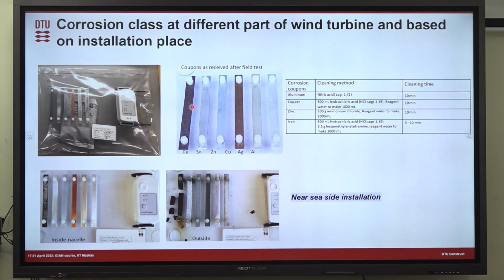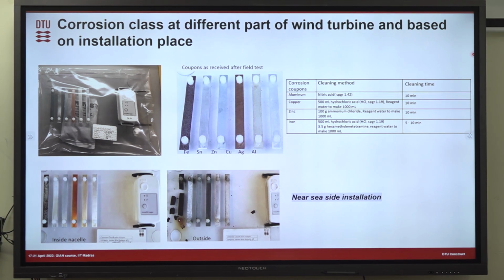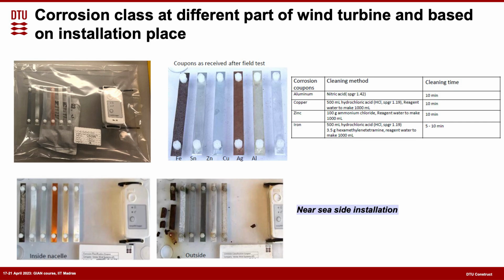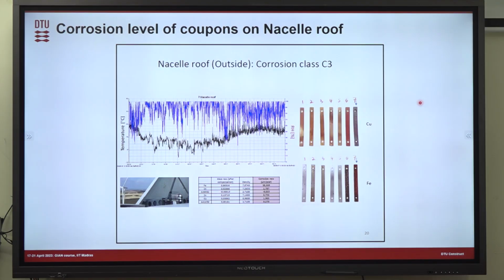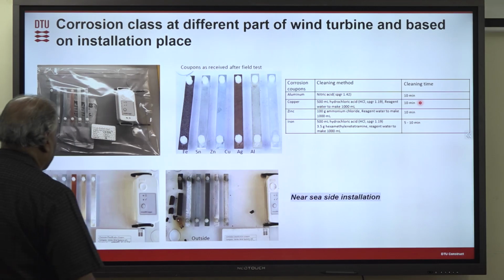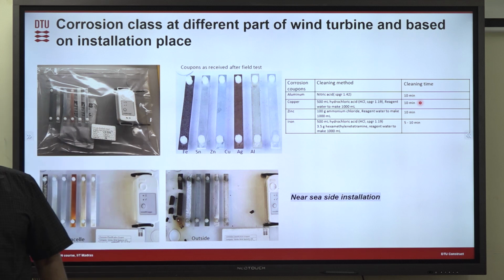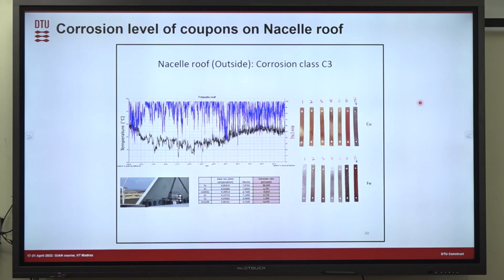So what we do is take these coupons and remove the corrosion product by a cleaning method. For copper and silver, we can also do an electrochemical reduction process, to reduce the copper oxide and silver oxide, but for the other metals we cannot do that, so we use the cleaning process, and then we analyze how much has corroded. I'm not showing everything, but we also do SEM, scanning electron microscopy, and things like that to get a detailed idea about what is happening.